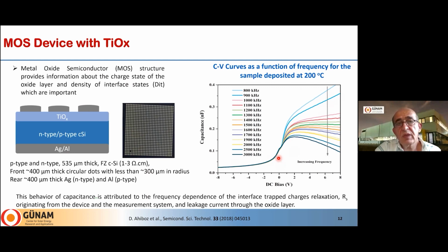We have an accumulation-like capacitance curve for the positive voltages, and inversion-like curves for the negative voltages. And there is a strong frequency dependence for the positive voltages, which shows that some electrons are stored in the structure, and the storage time is compatible with the frequency of the signal.